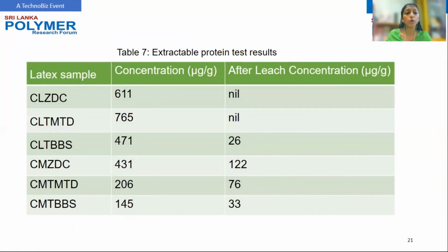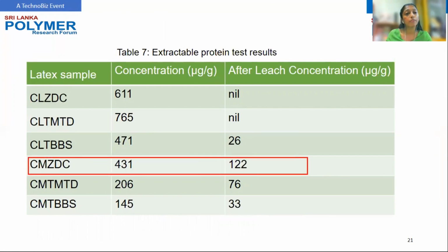After leaching, water-soluble proteins were extracted more from cream latex with a ZDC accelerator than other samples. Before leaching, protein content was lower in cream latex than centrifuge latex. So, creaming, pre-vulcanization and leaching steps can be used in the manufacturing process to remove a significant amount of extractable proteins.